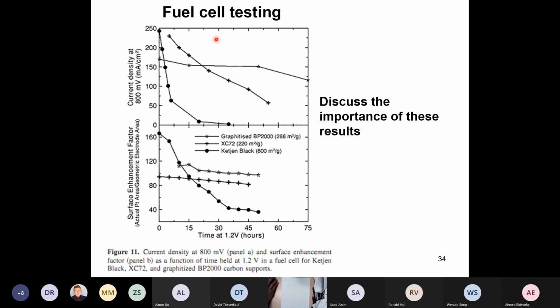Okay, so here's an example of the importance of graphitizing the carbon. This is some work that was done at 3M. What they did here is they exposed a cell to 1.2 volts for certain amounts of time. Okay, so 1.2 volts is a good way to kill fuel cells. A fuel cell's open circuit voltage is more like 0.85 volts. We'll learn why in a minute. And if you hold it at 1.2 volts, you're in a region where carbon corrosion happens really quickly.